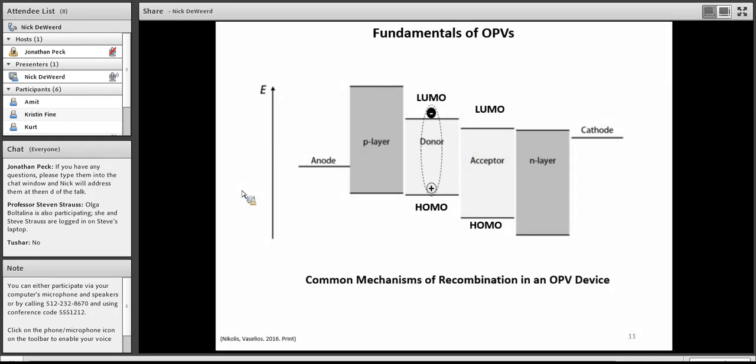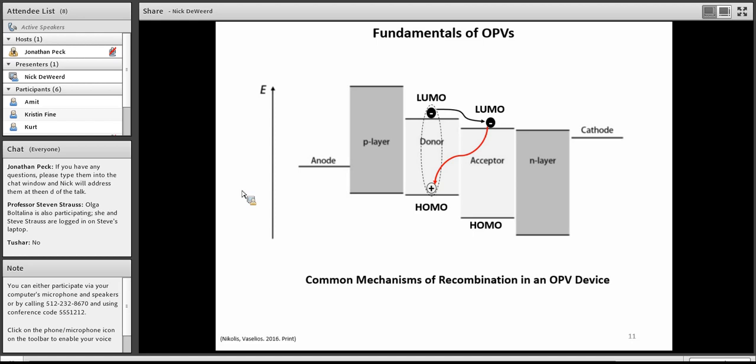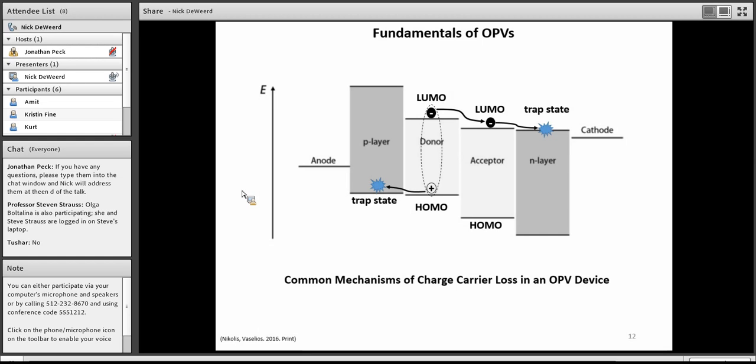We do also care a lot more about recombination in OPV devices. That's predominantly because the number of charged carriers at any one time in an OPV device versus a traditional photovoltaic is much lower. The first and most obvious recombination is a straightforward recombination of the exciton to the hole pair if it does not delocalize or hop to the acceptor LUMO. But then let's say if it makes it to the acceptor, then there's obviously the second recombination is geminate recombination where the now delocalized exciton manages to find a hole and recombine. And then lastly, there is the dreaded trap state. These trap states are inherent in both photovoltaics and OPVs. But in OPVs, the trap states can come through a lot of different chemical degradation processes that can take place in the device.